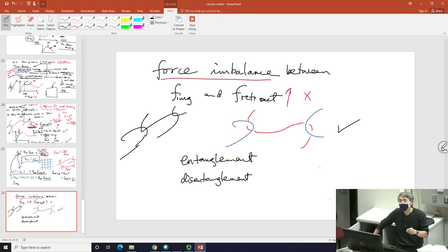There is entanglement in the linear response sense, in the quiescent sense, where you have a tube-like confinement due to uncrossability. But there's another type of entanglement we're talking about. We're talking about when I stretch, do I still have entanglement? By that, I mean, when I stretch between the entanglements, can I stretch this strand? That would be another way of defining that entanglement exists.